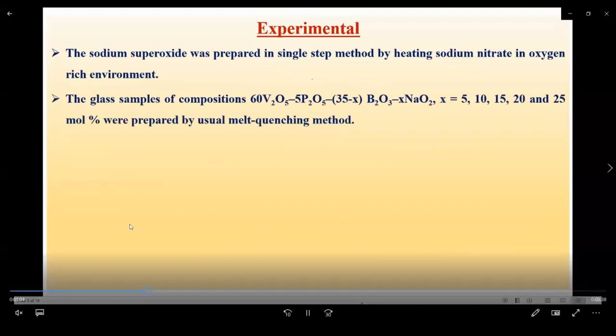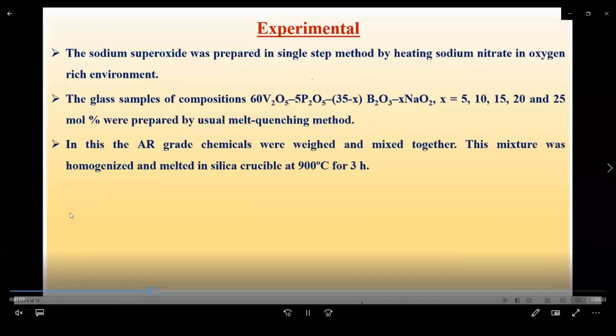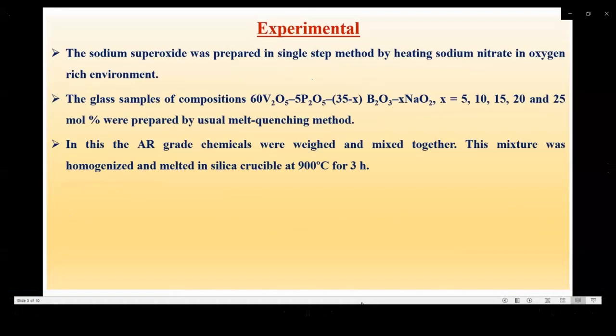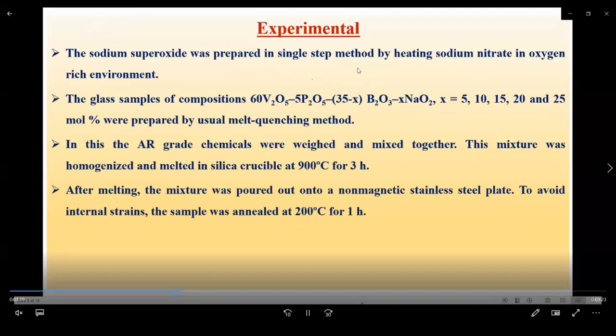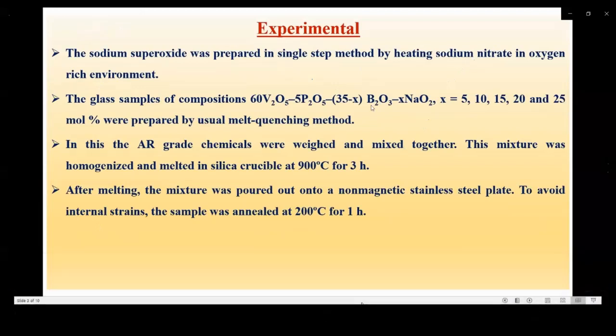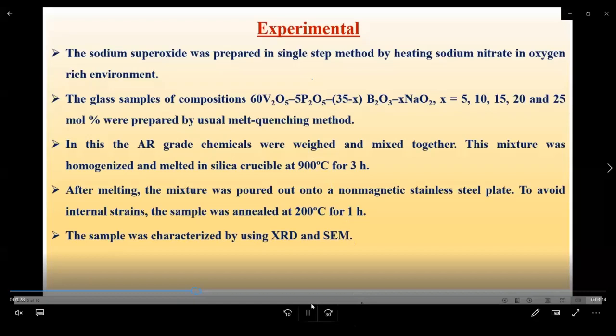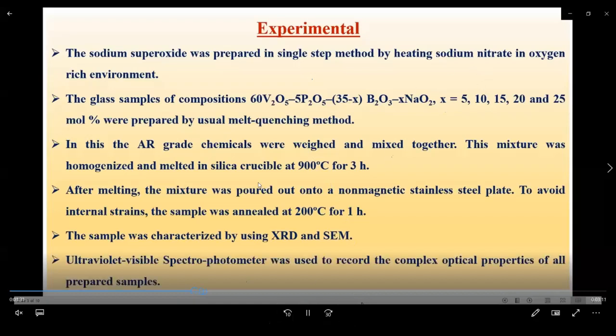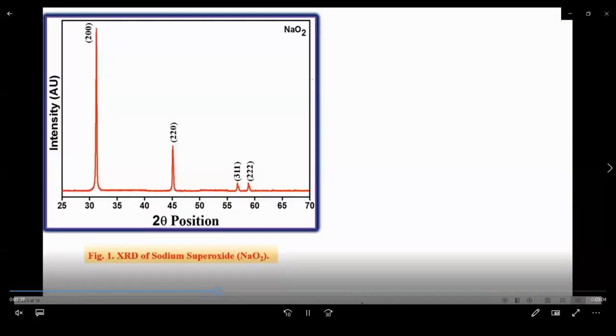The various glass samples were prepared by using the usual melt quenching method. In this, the AR-grade chemicals were weighed and mixed together. This mixture was homogenized and melted in a silica crucible at 900 degrees Celsius for 3 hours. After melting, the mixture was poured onto a non-magnetic stainless steel plate. To avoid internal strain, the sample was annealed at 200 degrees Celsius for 1 hour. The sample was characterized by using XRD and SEM. The UV spectrophotometer was used to record the complex optical properties of all prepared samples.